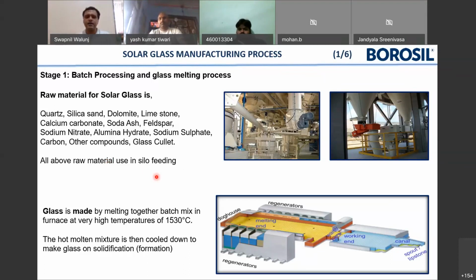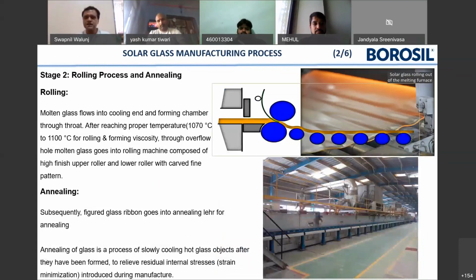Then when the batch mix is molten, the hot molten mixture is cooled down to make solid glass, which is called the formation process. So batch processing and glass melting is something that we have seen. Then the glass rolls out of the furnace, and the process is called the rolling process. The temperature comes down to around 1100 degrees Celsius. It is then passed between two rollers. These two rollers impart a particular texture as well as thickness to the glass, and ultimately on the lower rollers the glass comes out. You can see the glass coming out of this furnace and getting rolled on the rollers.